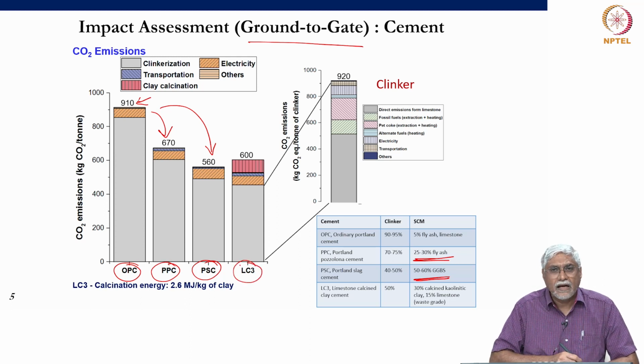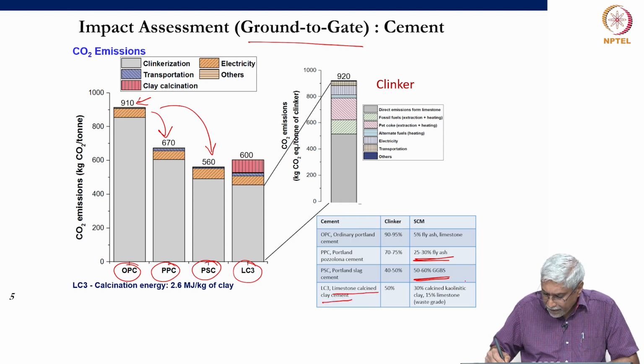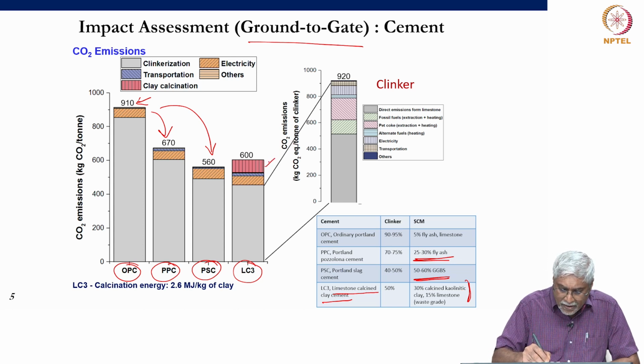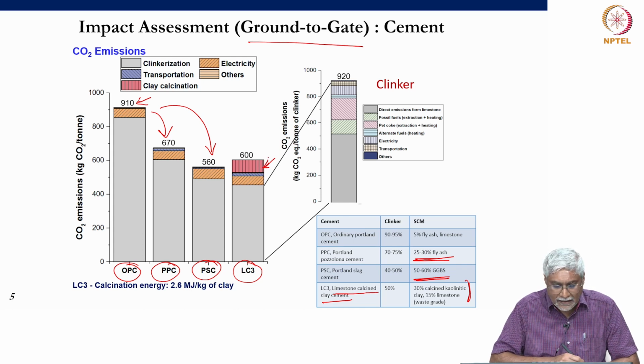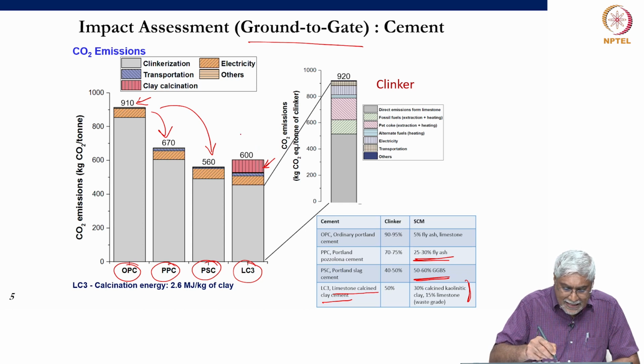LC3 is a new type of cement that we have done a lot of work on. It stands for limestone calcined clay cement, where we have 50% clinker, 30% calcined kaolinitic clay and 15% limestone. And the limestone could be waste limestone. We are not using limestone that is meant for cement production. And here we have again the calcination of the clay. So, there is some impact of the calcination of the clay, and that is what you see here in this red part of the bar diagram, giving us a carbon footprint of about 600 kilograms of CO2. So, this is also lower.